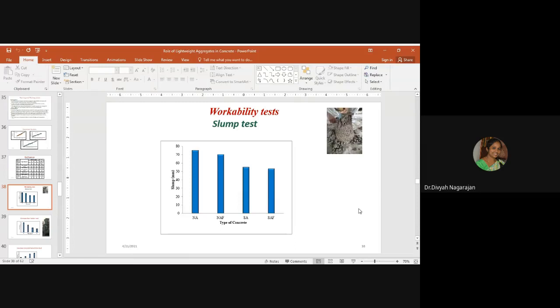Coming to the workability test. According to the IS code of practice, the slump value has to be between 50 to 100 mm for medium workability for use in structural concreting. This is applicable in the case of normal weight concrete. However, when there is deviation in slump, it can be adjusted during mix proportioning. Addition of basalt fiber to the mix affects the workability of the concrete. It reduces the workability initially, but adjustments in the mix by using the superplasticizer maintained the workability.